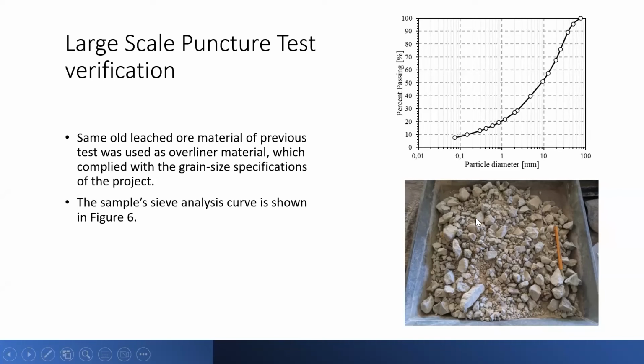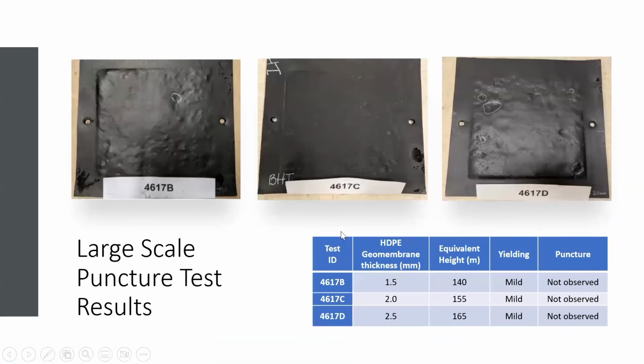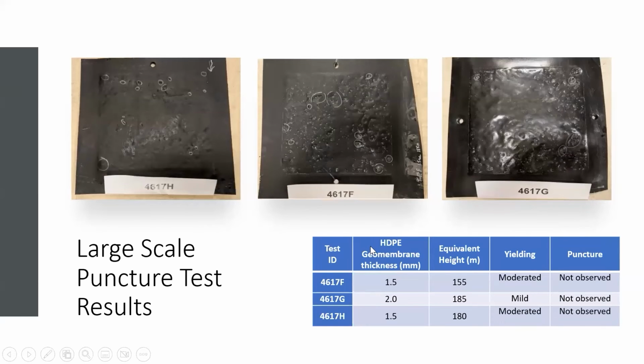And this is a material that looks very, very aggressive in this case, in contact with the geomembrane. And the results for each stage are the following. For the first, we have between 140 meters to 165 for each of the thicknesses here, and the results look like mild yielding and no punctures were observed. In the second stage, we are talking about heights between 185 and 180 meters for 2 millimeters and 1.5 millimeters. Results show mild to moderate yielding in this case, as you can see in the pictures, but no punctures were observed.